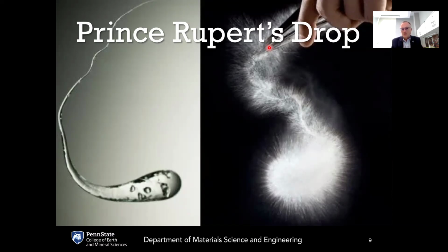It's basically an explosive fracture because there's so much stored tensile energy being released so quickly that it leads to enormous acceleration of the crack tip, which leads to very early branching of cracks. Each crack is so short and branching so quickly that ultimately it goes back to dust. The pieces are just so small. So this is an example of an extreme case of frangibility because of the large amounts of tensile energy that are stored.